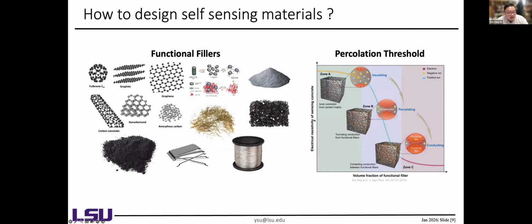But how to design the self-sensing material? As I said, this material has been developed, proposed and investigated for a few decades, but it's all at small scale. So we wonder about the large scale. It's really critical to select the functional filler, or conductive filler. Especially when we select that, one thing we need to take care of is the percolation threshold, which is that we cannot make the material too conductive or make the material too insulating. So we need to find a point in between.